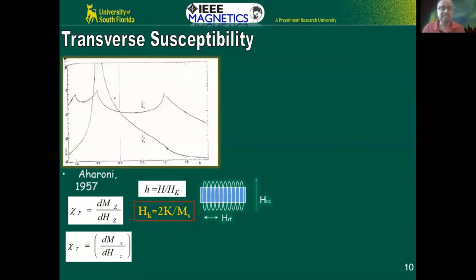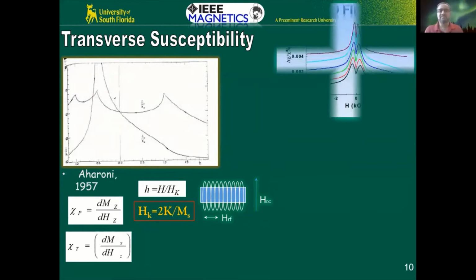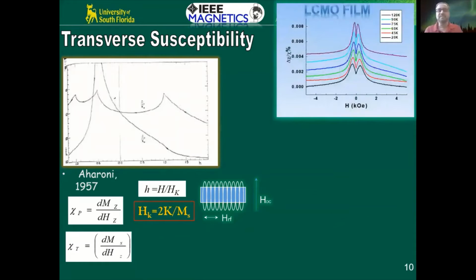We tried to set up an experiment to measure what Aharoni predicted all those years back, and we were successful in doing that. This is one of our signature experiments that made us really well known in the magnetic nanoparticle community, because we can measure these anisotropy peaks very, very precisely. We've been looking at this for many years on many kinds of magnetic particles, magnetic films. So you can see that this is our data here.